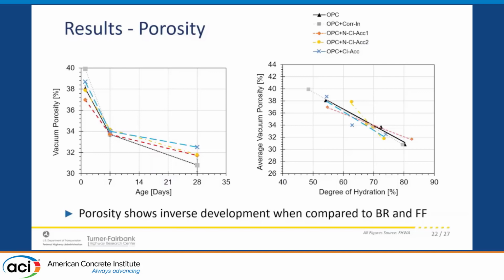And again, we have opposite trends, of course, because resistivity goes up over time because we're densifying the microstructure, and porosity is going to go down over time because we're reducing the overall porosity as the cement hydrates. Similar trends, but in the opposite direction. And once we account for degree of hydration, not so much difference among the different admixtures.